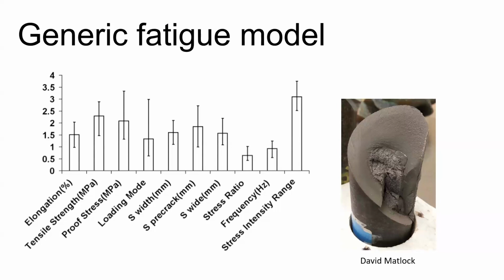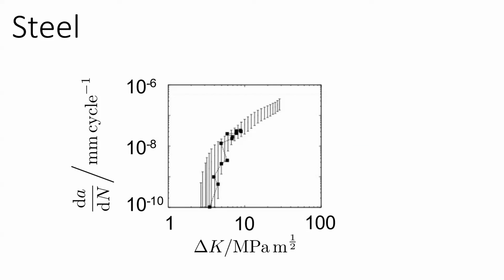So I'm going to show you quickly an amazing result, all right? This is the fatigue of steels, and most steels break by fatigue. 95% of all failures are due to fatigue. This is from Colorado School of Mines, where they have a large range of samples. And I created a machine learning model, including these variables, because I have a lot of data on steels, right? Huge quantities of measured data. And the axis here simply represents the significance of each variable in explaining the fatigue life. When we plug in steels without any information about them in the original database, we get good agreement in the crack growth rate as a function of the stress intensity range.